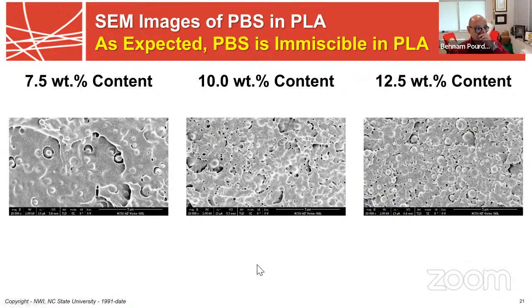These materials are not miscible. So you can look at these blends. You can see the large particle sizes of these. Of course, if you go to very low amounts, it doesn't really impact your melt strength of the polymer. But if you go to higher amounts, you would have an issue. With filament spinning, you're probably limited to about 12.5% of addition of, say, PBS in PLLA. And beyond that, you would get breaks in the structure.